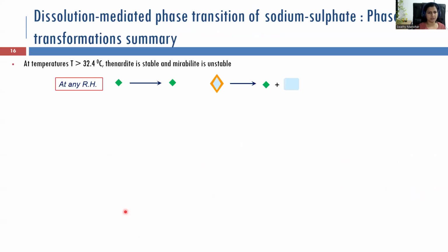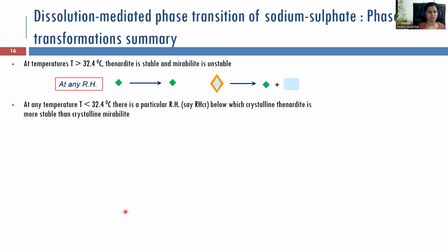Now I'm explaining what I told in previous slides in a bit more simpler way. At temperatures more than 32.4 degrees Celsius, based on the previous phase diagrams, only thenardite is stable and mirabilite is unstable - so green is thenardite. At whatever the relative humidity is, if the temperature is higher than 32.4 degrees Celsius, mirabilite will go and convert to thenardite and water. So you will see only thenardite in those systems.